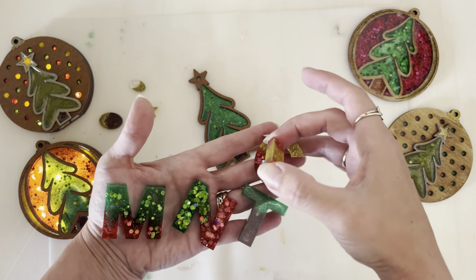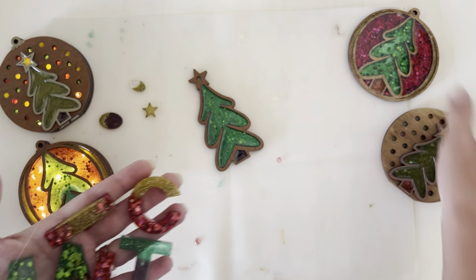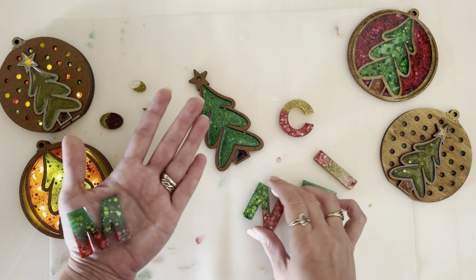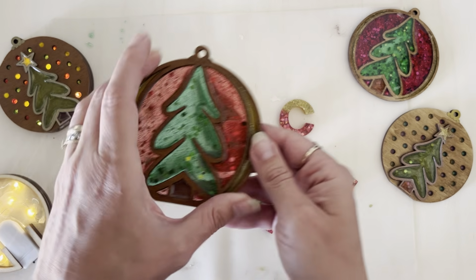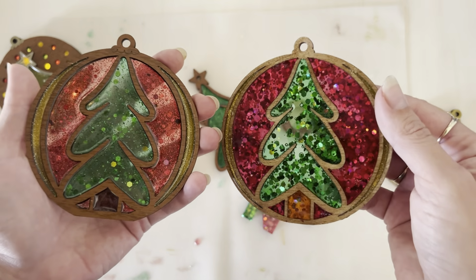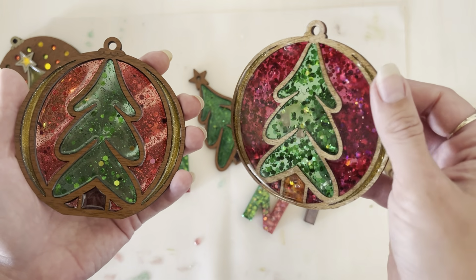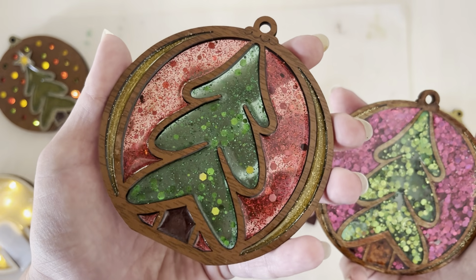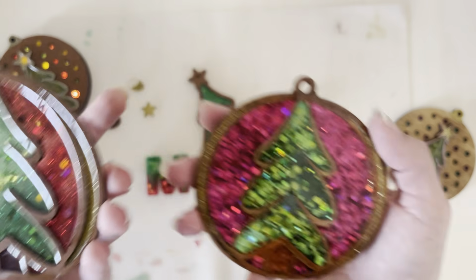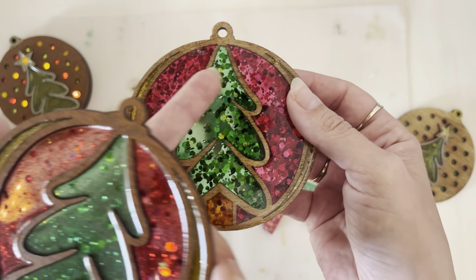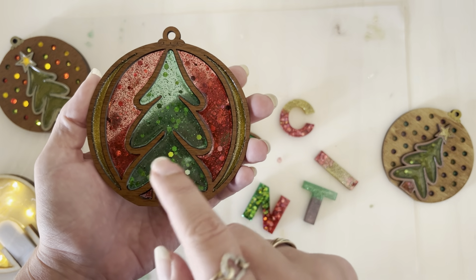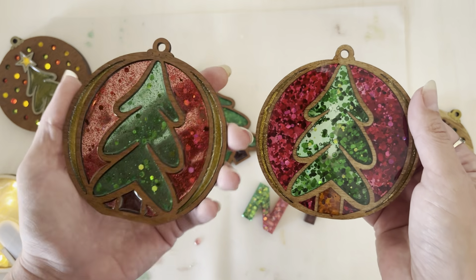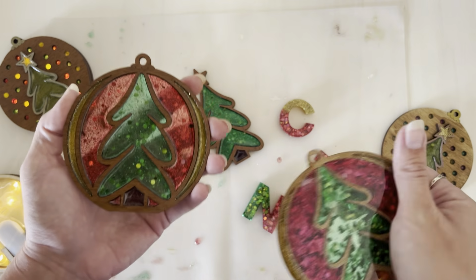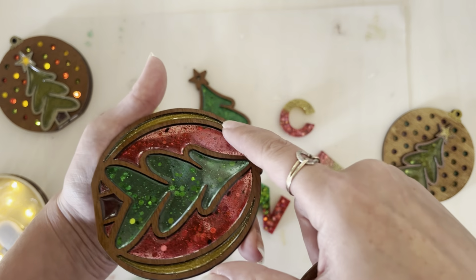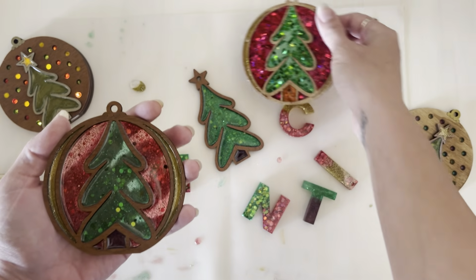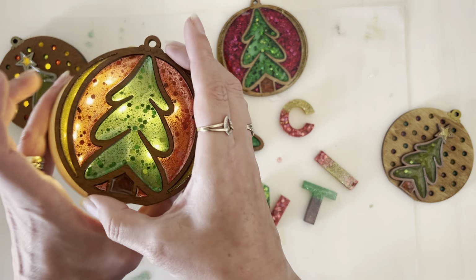So these were from my remaining epoxy resin, and also you might see the difference if we just put these down again. From this front to the one that I did with UV resin. So I didn't apply as thick as a coat as I did on this one, but there's hardly any bubbles, if I even have any. I don't think I have, compared to the UV resin. So the regular resin is actually easier to work with and will give you a prettier result in the end. And you can of course top this off with additional resin, but I actually like that you have this roof because it will make it look more like it's stained glass.